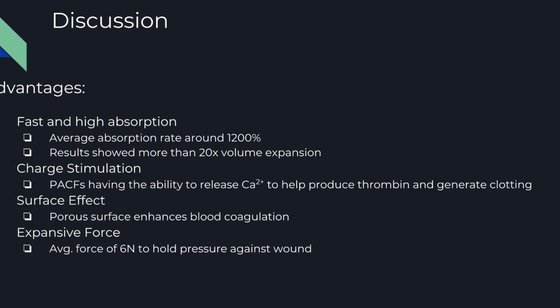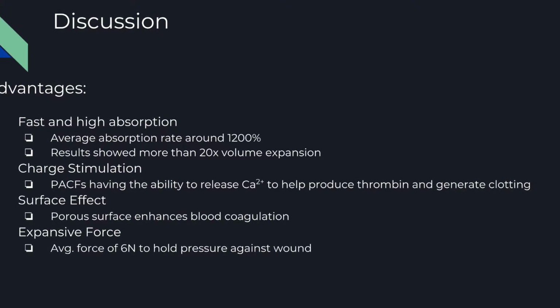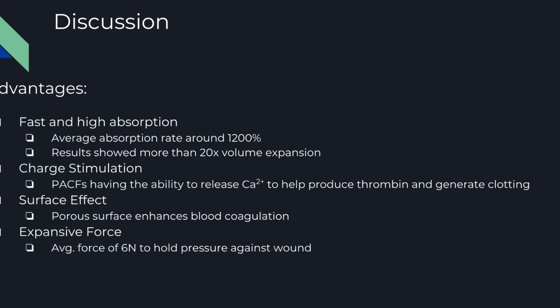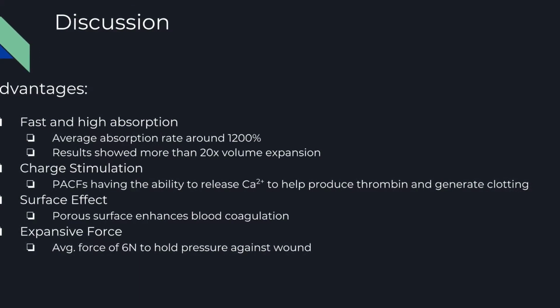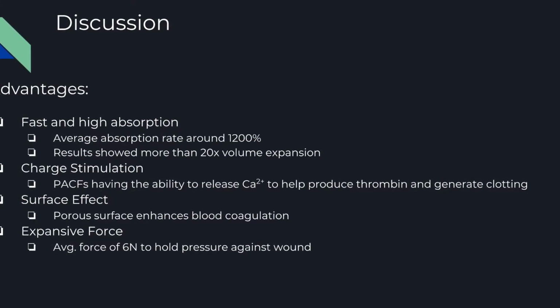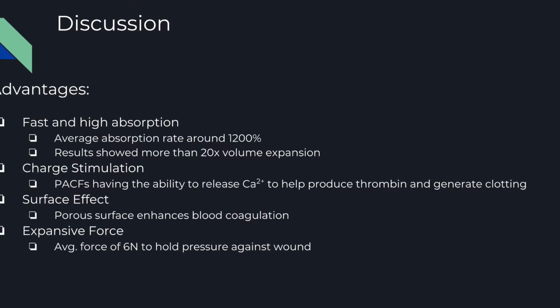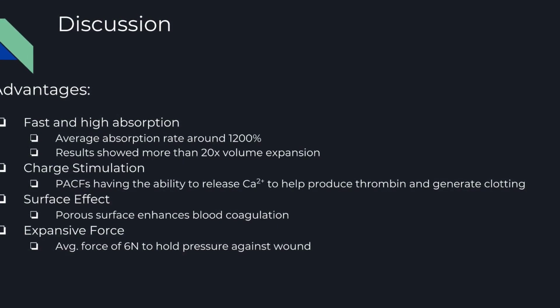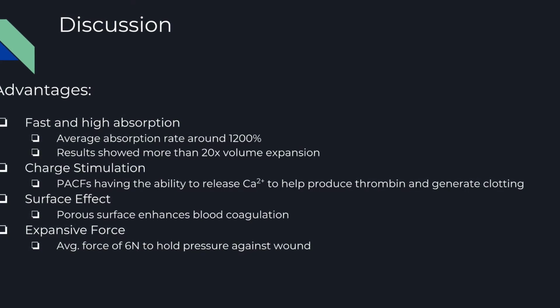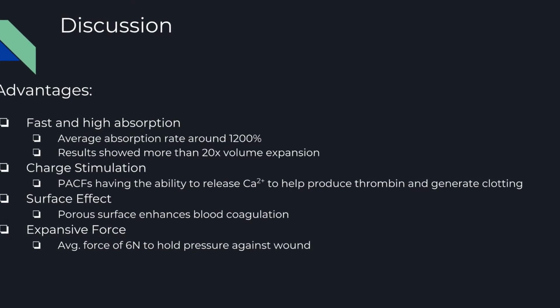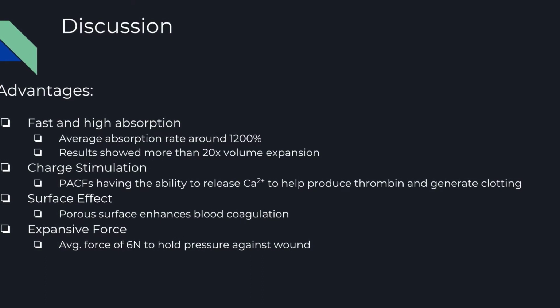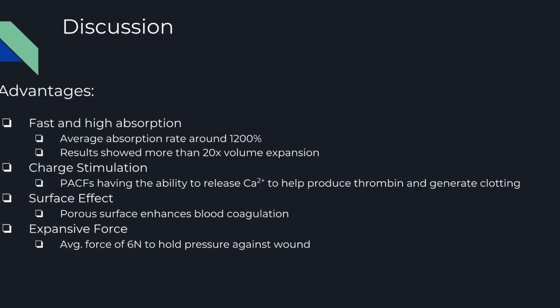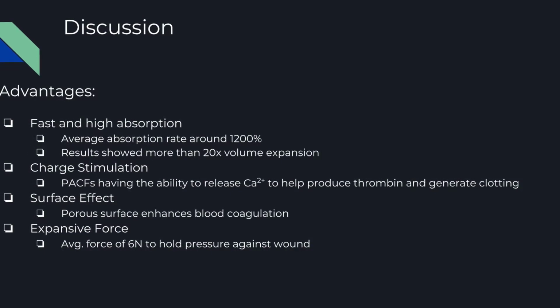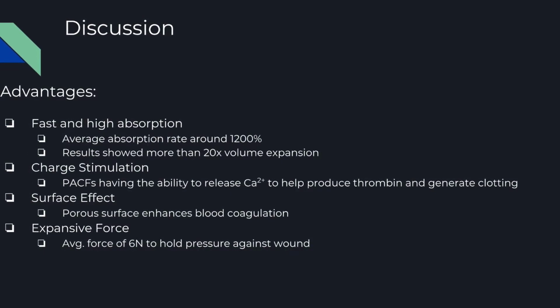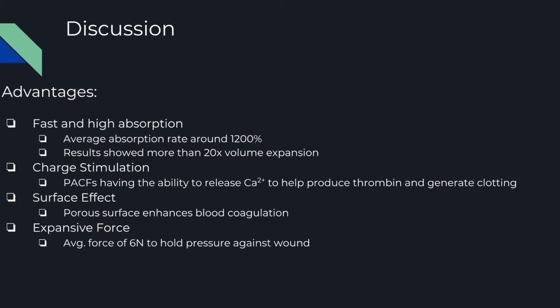The first advantage of this material is the ability to have a fast and high absorption rate. This is crucial in order to rapidly stop bleeding and hemorrhaging on the battlefield, allowing for more time to reach medical attention. The average liquid absorption rate of the composite foams was more than 1,200%, which is favorable for rapidly absorbing plasma. Experimental results showed that the PACFs could be delivered into the wound cavity in the shape of small particles and undergo more than 20 times its volume expansion to fill large cavities, which is more than 10 times larger than the common hemostatic materials on the market.